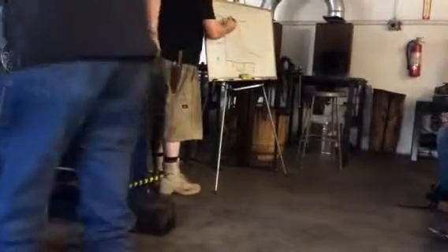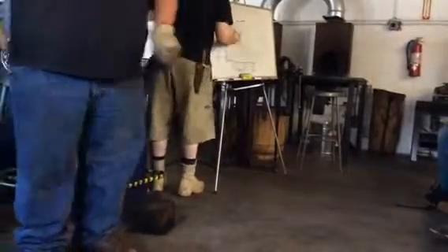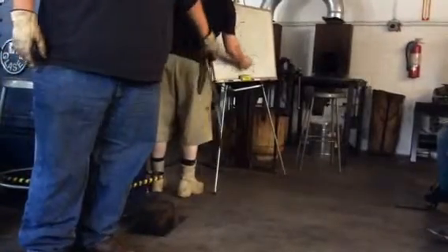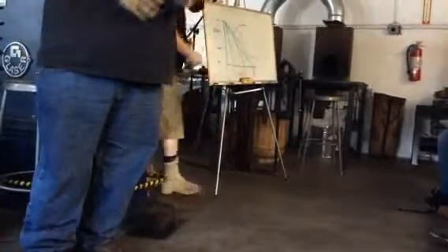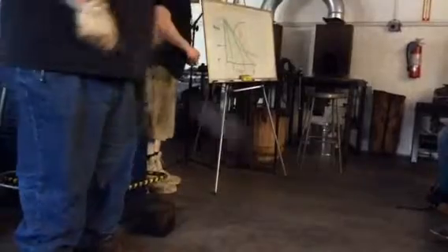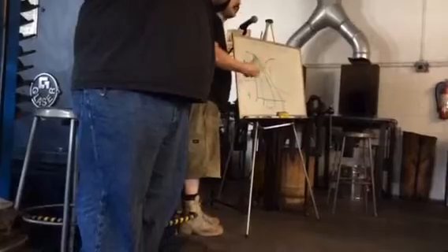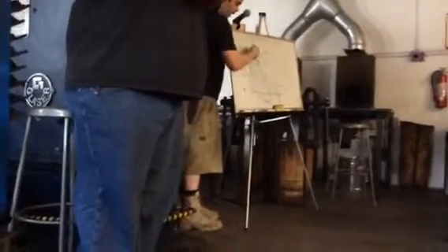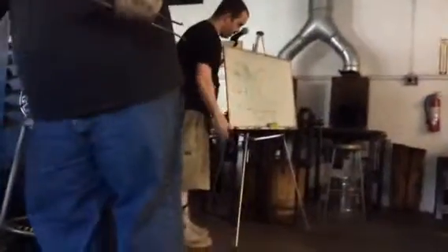So you have three cooling curves. You have one where it takes 2 seconds in a slow oil, one where it takes 1 second in a moderately slow oil, and one where it takes 0.5 seconds. That's like a fast oil, like Parks 50, which should be used for a steel like this, or any of the simple steels, like 10xx. Parks 50 is a fast oil, and it just gives you the ideal cooling curve for this, so that you won't fool around.